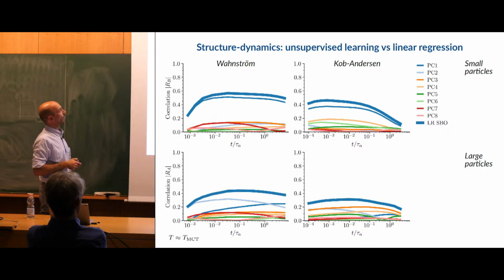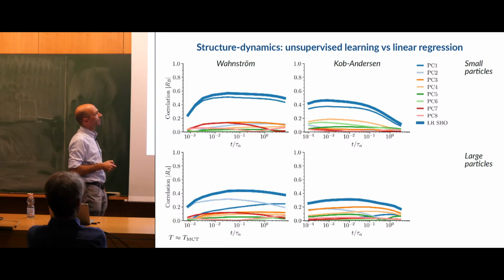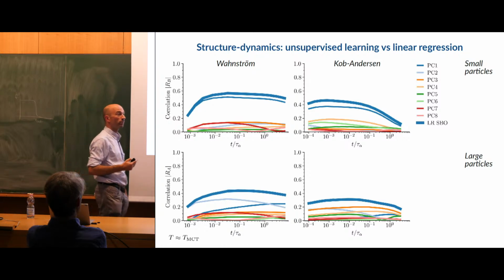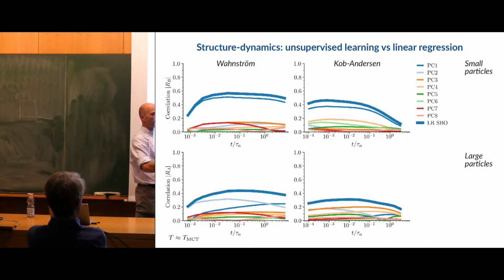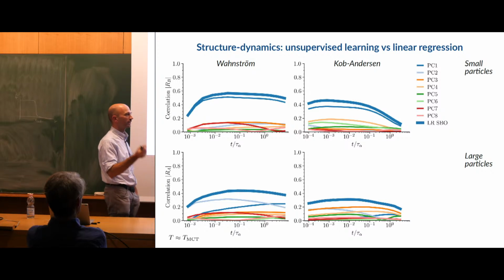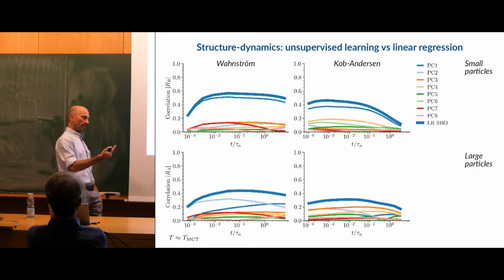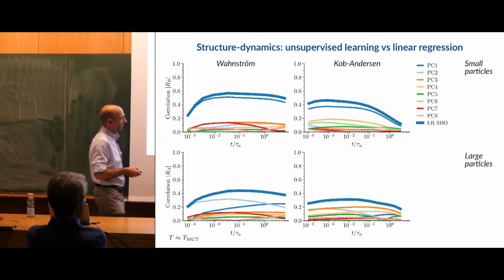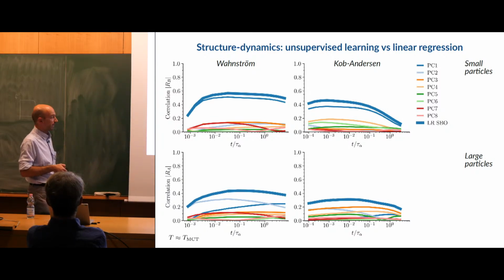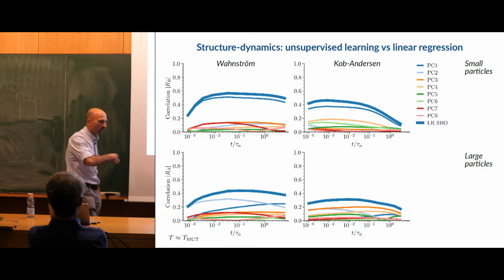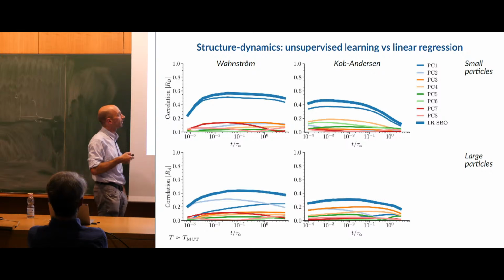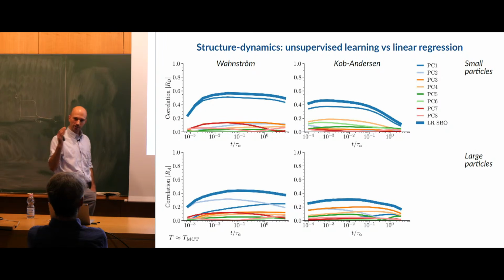And as we can see, around small particles, things are easy. Because with the first principal component, you already get essentially the bulk of the signal that you would get with a whole descriptor. So there's a very well-defined measure of local order that captures the bulk of the signal that you can get, at least with this descriptor. Things are more tricky around the big particles, where you see the correlation is spread and it's weak. It's weak and it's spread over all the principal components. And when you aggregate them together, you get something like this, which remains a weak correlation, I would say, not so strong as around the small particles. So there's a difference here.